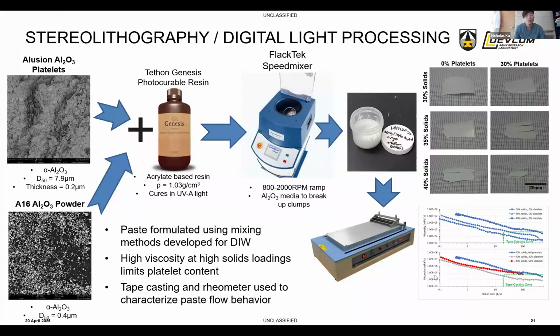And then also the material itself, right? In our previous work, we're much more interested in carbides and borides. These are relatively dark powders with high refractive indexes. We spent a lot of time spinning our wheels trying to figure out if we can get any appreciable depth of cure, but because of how much these scatter and absorb the light source, you can't really do high refractive index materials using this AM process. So we're really left with the white powders, the oxide powders I showed on this slide, like alumina, which could definitely have some applications in transparent materials or RF-based materials, so dielectrics, which is where we're targeting this technology.